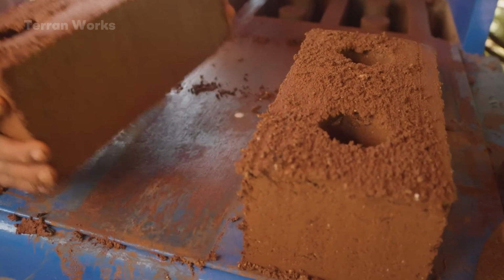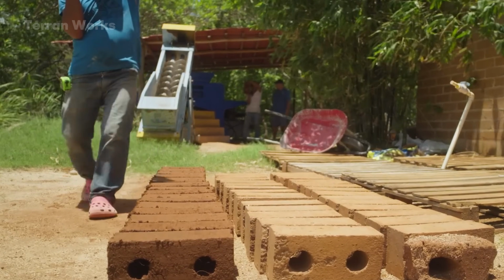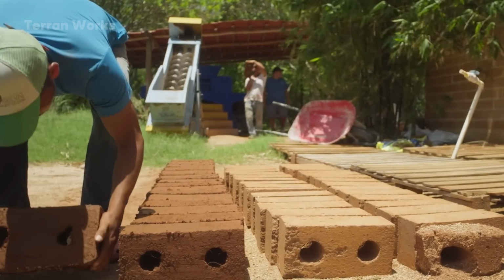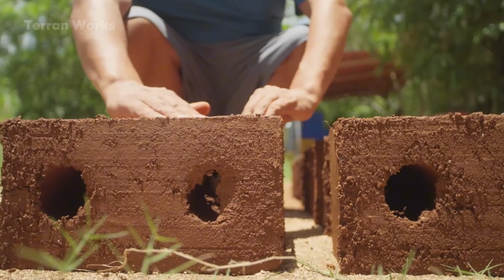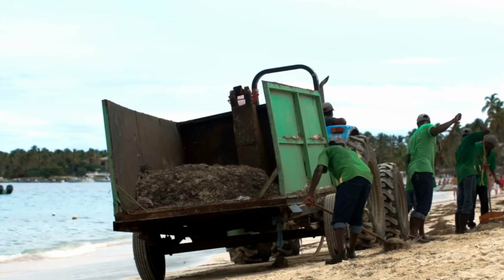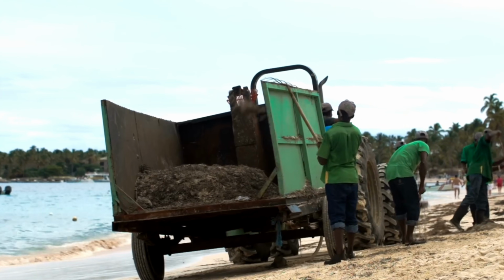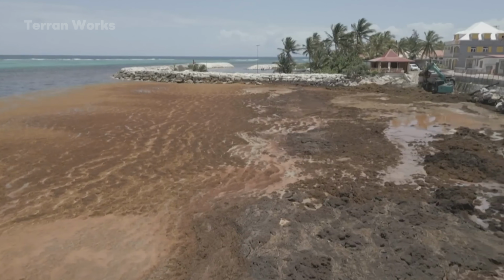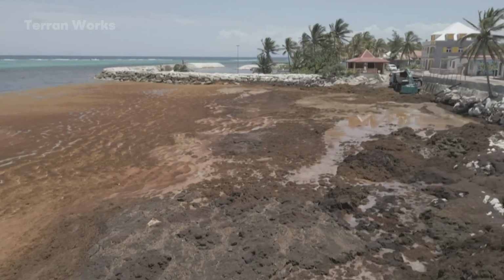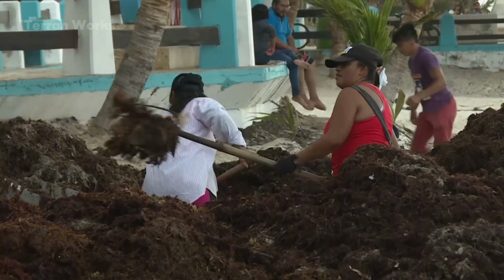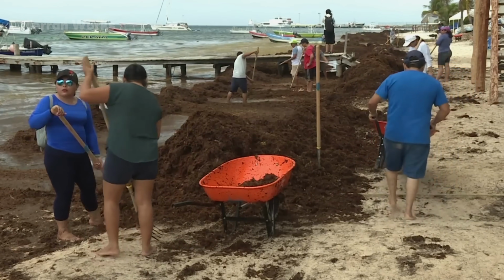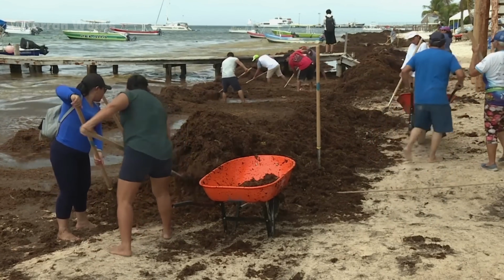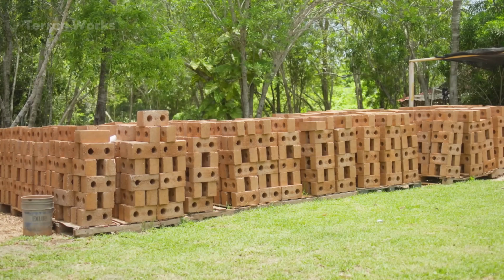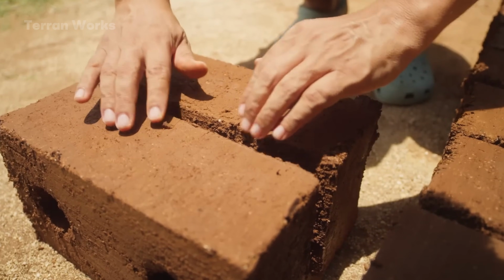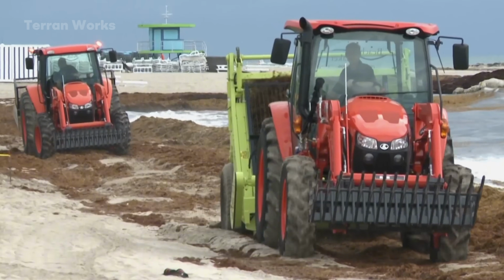Early test batches cracked due to salt crystallization. High moisture reduced compressive strength. Residual organic odor triggered community opposition. Building standards had no evaluation framework for seaweed bricks. The project nearly stopped several times. After many rounds of salt washing, blending, and layered pressing, the team produced bricks durable enough for real use.